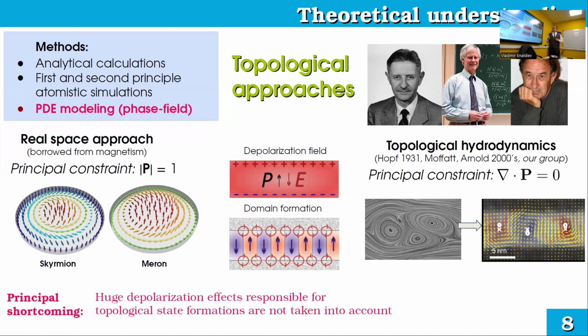It's the so-called real space approach. And what is important, in magnetism, there is a constraint of the order parameter to be constant, while in ferroelectrics, the main constraint is the divergence of polarization to be equal to zero. Because in ferroelectrics, long-range electrostatic forces, depolarization electric fields, play a crucial role.